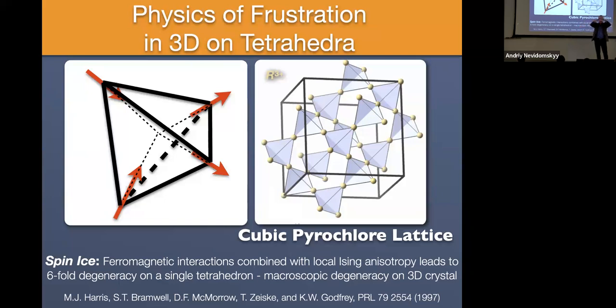And in fact, the degeneracy scales so quickly that you get what's referred to as a macroscopic degeneracy, which is a degeneracy that's big enough to give you a residual entropy, even at zero temperature, that precludes the possibility of an ordered phase. There's too many choices, basically, for the spins. And that problem that I just described is referred to as the spin ice problem. Okay? And this is the discovery paper associated with it.